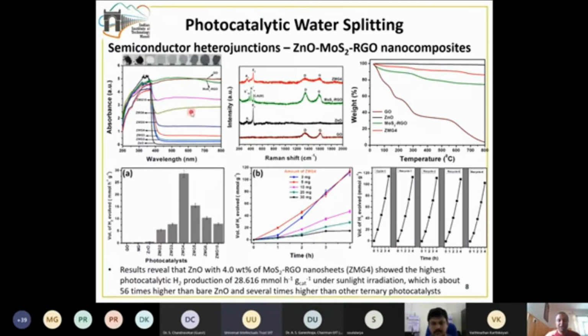Now comes the main question. We prepared this nanocomposite thinking that we want to absorb more of the visible light radiation, or the majority of the sunlight radiation, because zinc oxide has the capability to absorb only the UV radiation, which is from 200 to about 400. You can see that the zinc oxide absorbance ends at 400. But when we prepare these nanocomposites in varying proportions, we can see that slowly the absorbance in the visible light region also increases. So this is the most important thing for this particular work.